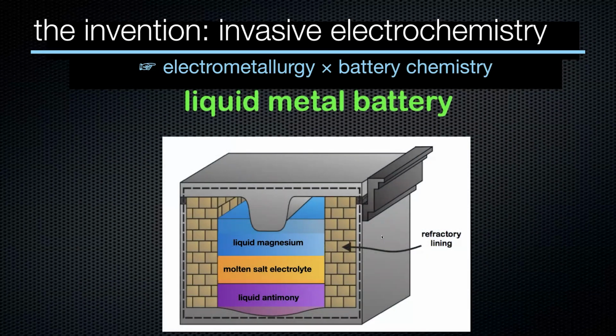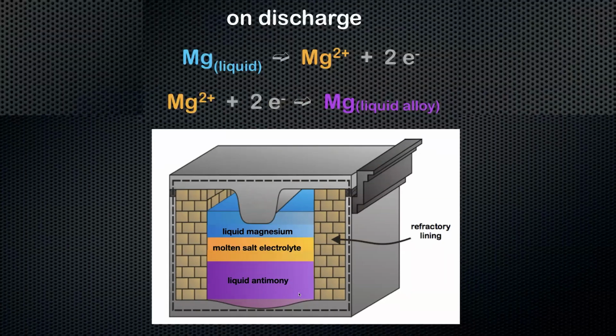So this is the earliest conceptualization of the liquid metal battery with 3 layers, a low density liquid metal on top, that's magnesium, and a high density liquid metal on the bottom, antimony. And there are different parts of the periodic table. Magnesium is a good metal, good electron donor, and antimony is a poor metal. It's a good electron acceptor. And in between, we have a molten salt electrolyte. And the metal is insoluble in the salt, and the salt is insoluble in the metal. And so the 3 layers lie one above the other in order of density. There's no membranes, no separators, and so on. So that was the concept of the liquid metal battery.